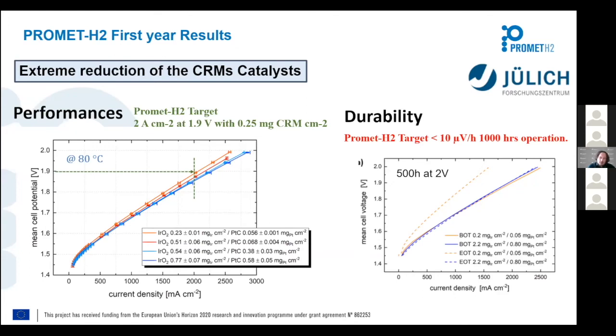I would like to draw your attention to the orange curve that is a precision curve that was loaded only with 0.23 milligram per square centimeter of iridium. That is very, very low compared with the current state of the art.